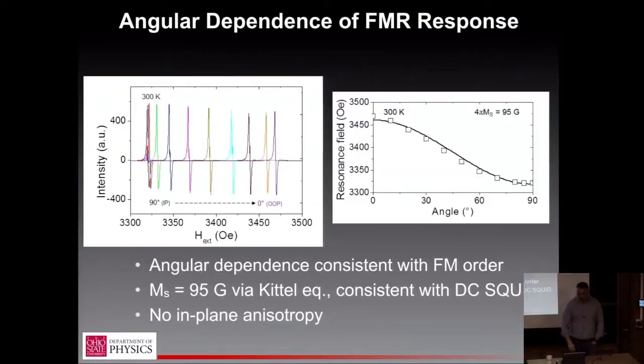But then when we varied the angle of the DC field from in plane to out of plane, which is a classic FMR measurement to measure the anisotropy due to the shape, you can see the line shifts exactly as anticipated. You get a sinusoidal variation here. You can fit that using the Kittel equation and extract the saturation magnetization, which is pretty closely consistent with what you get out of SQUID data.